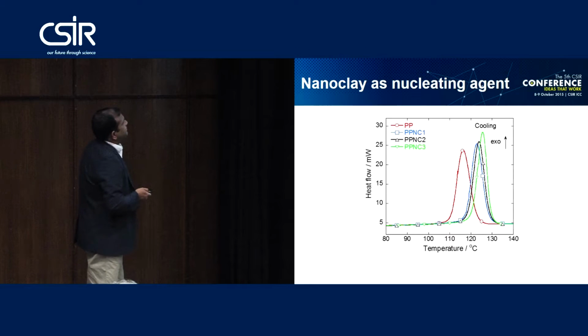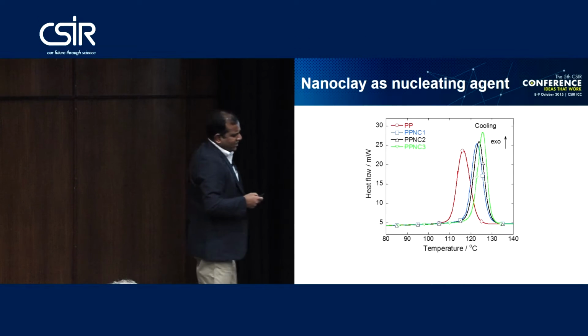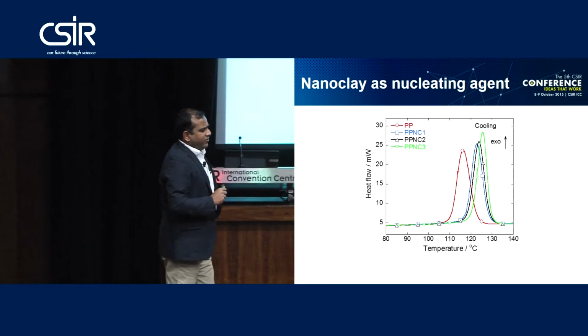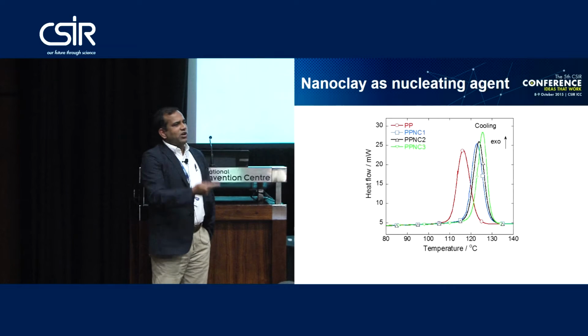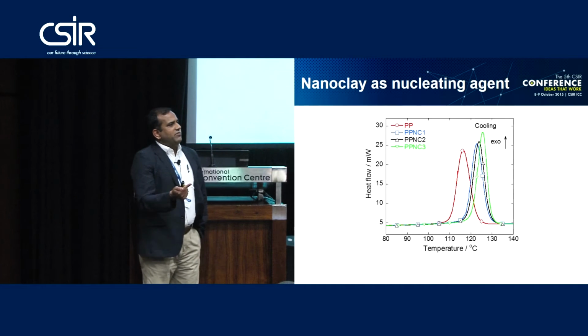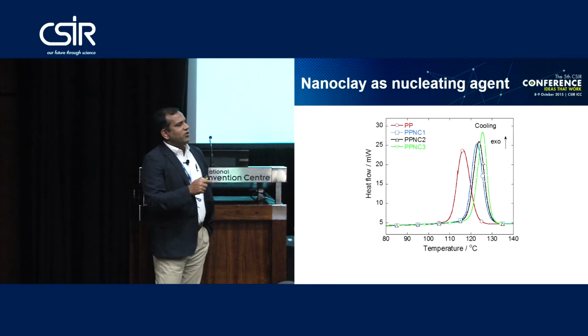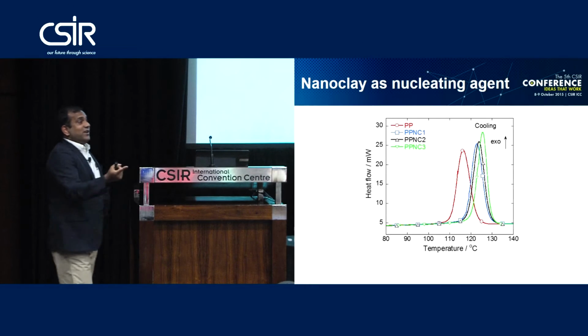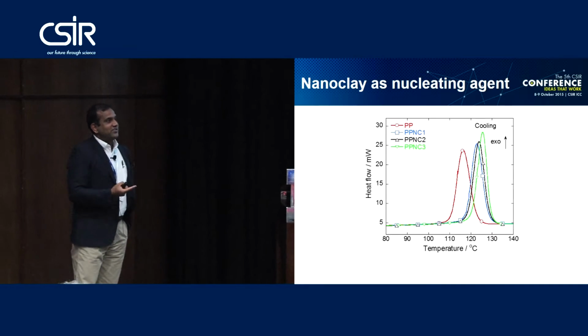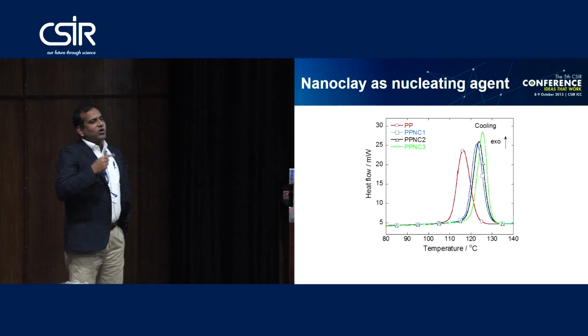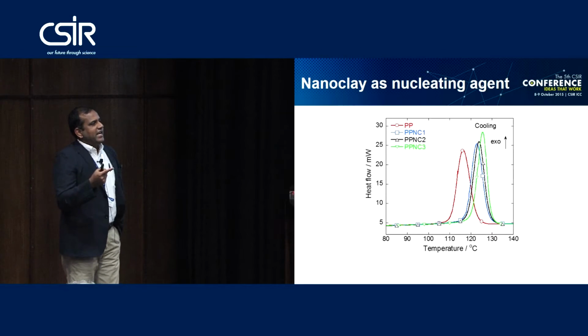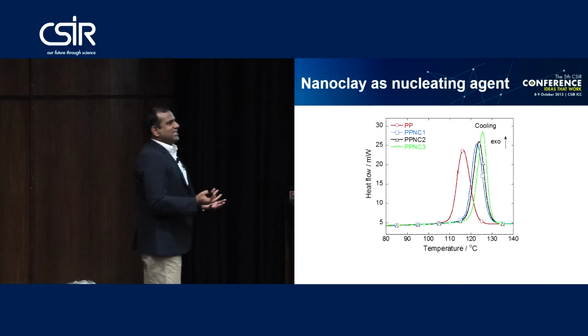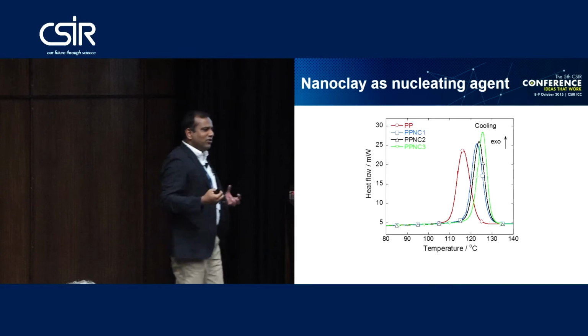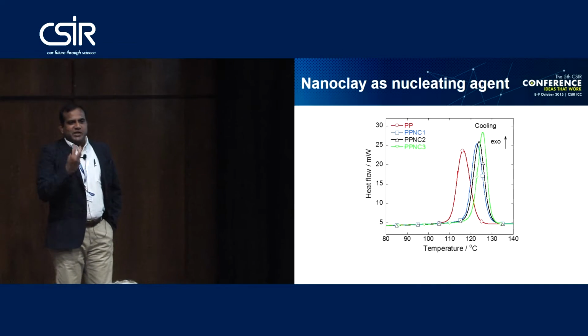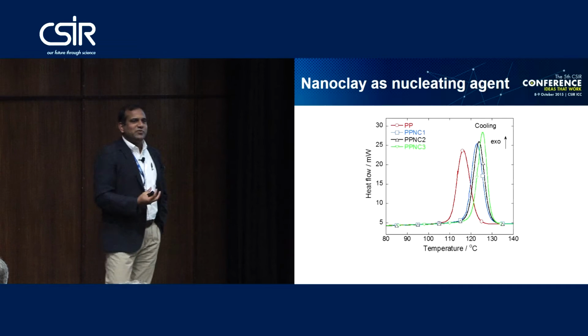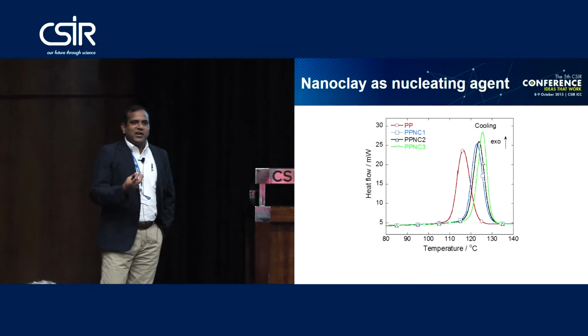One of the biggest challenges, particularly in the polyolefin industry, is how to mold polyolefins, particularly polypropylene and polyethylene, the kind of polymers we use every day, at higher temperature. Because every industry is going for an energy efficient mode. If you want to mold at high temperature, your mold must be solid at high temperature as soon as it comes out of the mold. That means your material must crystallize at high temperature. So you have to improve the crystallization temperature of the polymer matrix.